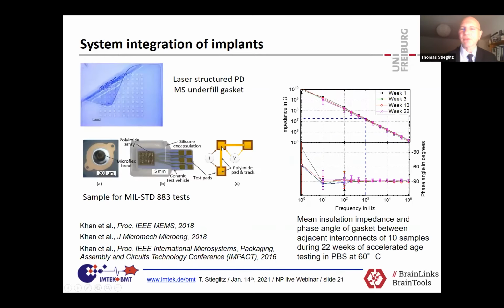For all the others, they go to the next slide, which is easier. We have here adjacent contacts, and we pre-manufactured a silicone rubber mat with holes where the contact pads are, and then we somehow glued by plasma activation this insulation sheet to the substrate, and glued our contact array on top and molded everything in silicone rubber. And I have to admit, we had to do some tricks so that the polyimide likes to stick to the silicone rubber. This is a quite complex process technology, but we made it work.